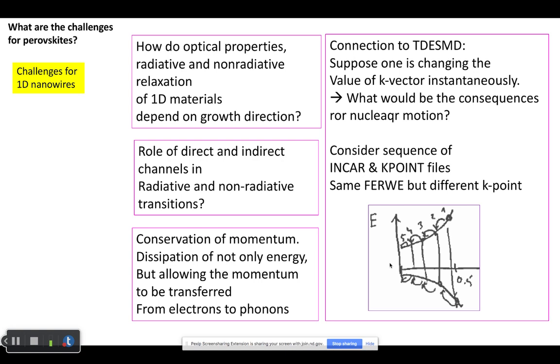This is challenging because we are based on molecular dynamics rather than normal modes with enabled momentum analysis. But what we can do, and here I see a connection to time-dependent excited state molecular dynamics that is pursued by Dr. Han, is that the research on one-dimensional nanowires can be tested in the following direction. One can practice the same philosophy as for TD-ESMD, creating several INCARs with different Fermi excitations. And in addition, one can create several k-points files. So at each time step of the trajectory, the script parses the right Fermi configuration and the right k-point configuration, and then continues the dynamics.